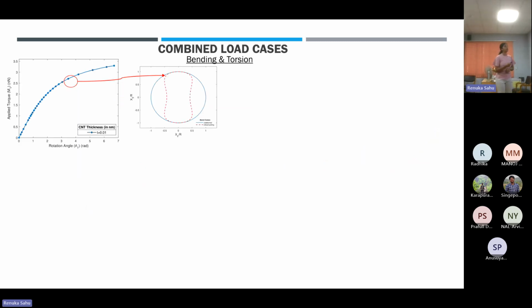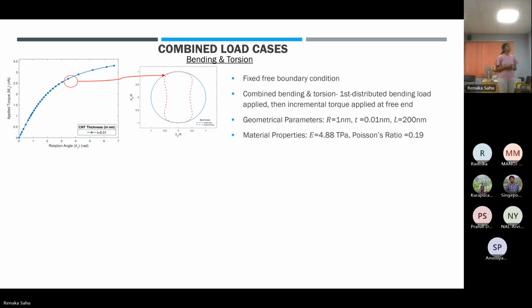We also did a combined load case of bending and torsion. Here, instead of taking the transverse displacement, we plot the rotation angle with respect to the applied torque, and we have similar kind of behavior. We are using fixed-free boundary conditions: first we apply the distributed bending load, and then an incremental torque is applied at the free end.